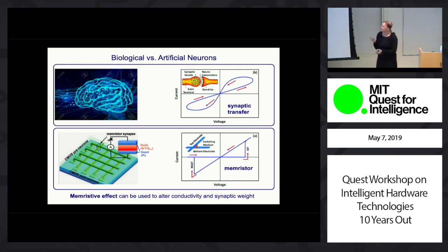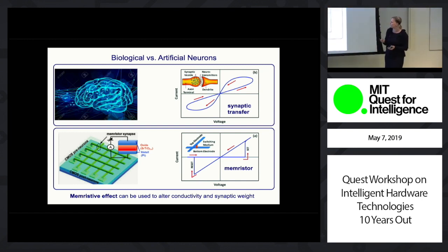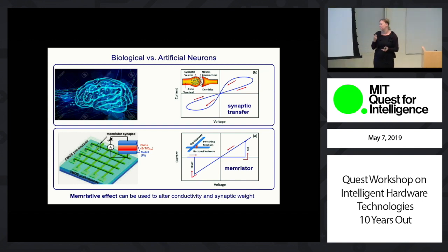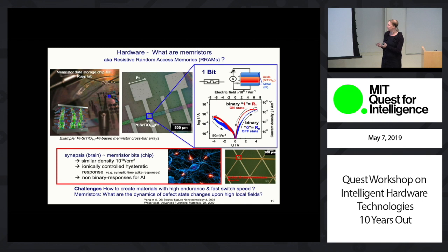And this gives you what you don't know from the textbook, where we normally talk about ohmic resistors, which would be a linear relationship. Here it gives you this hysteretic current-voltage profile, a characteristic time-retarded resistance response that you can tune with memristors.